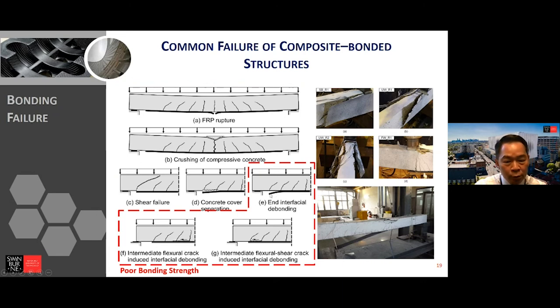Okay, and this may be due to high shear stress or peel off, and also interlayer cracking, shear cracking, in between the composite and the concrete surface. All these are very serious cases, because for this one you can see the damage, and for this one you cannot see it on the surface. And mostly, how people solve the problem, they just put an anchor mechanism at the end of the composite material. They may put a bolt to secure the ply end inside the concrete.